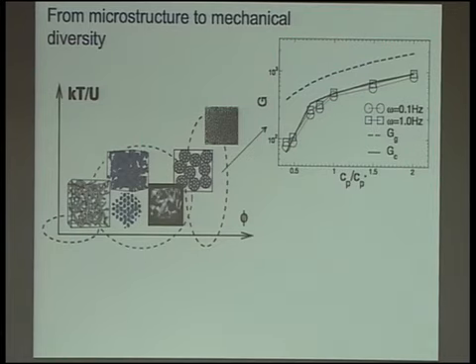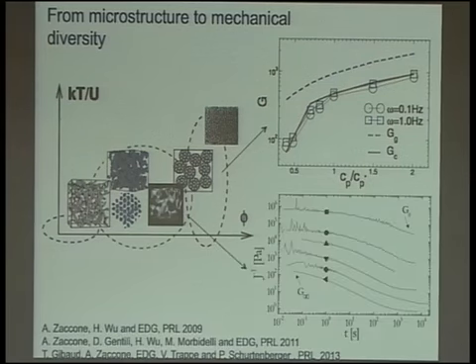This other example is taken from lysozyme, in a protein solution, where the strong attraction between the proteins can produce a complicated structure, a bicontinuous gel network, due to an arrested spinodal decomposition that is taking place. And a very nice set of experiments has shown that when you deform this system, you can get two very well separated, distinct elastic moduli, one that you can detect on short times, and then a distinct elastic modulus that you can detect at longer times.